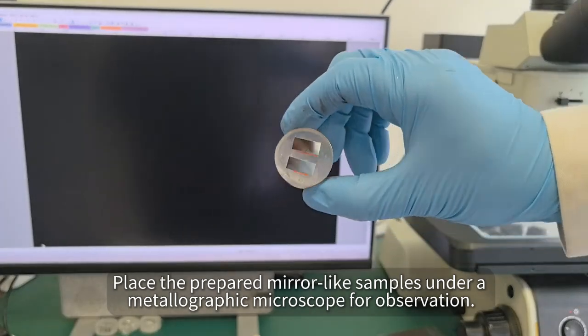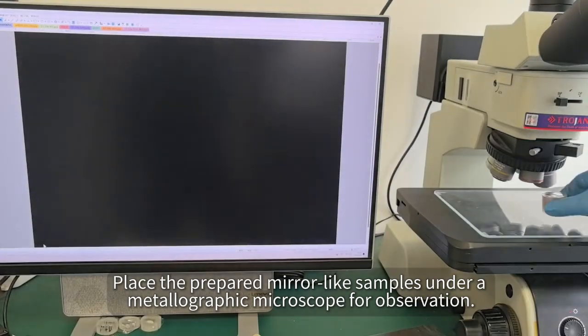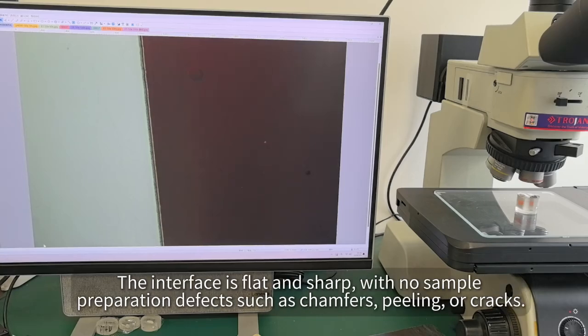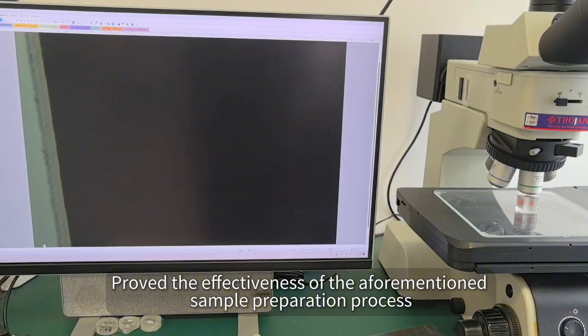Place the prepared mirror-like samples under a metallographic microscope for observation. The aluminum alloy matrix, the nickel intermediate layer, and the tin surface layer can be clearly observed. The interface is flat and sharp, with no sample preparation defects such as chamfers, peeling, or cracks. This proves the effectiveness of the aforementioned sample preparation process.